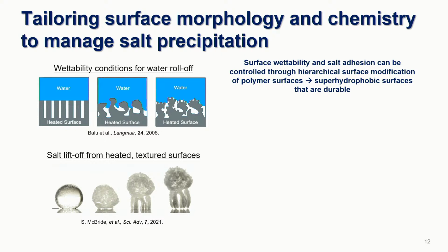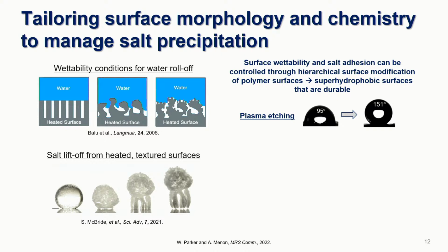And so we've been using a lot of tools in the IEN, and I have a seed grant from the IEN that's helped us look at low power plasma etching. So here's the contact angle on a polymer substrate without any surface modification. And then if we do this plasma etching process, so we use a reactive ion etching process in an oxygen environment, and we're able to modify the contact angle to get it to the superhydrophobic state. And if we do additional measurements on this, you can see that the droplet will actually roll off the surface as soon as we start tilting it. So it shows that it's also a very low adhesion surface, which is very important.